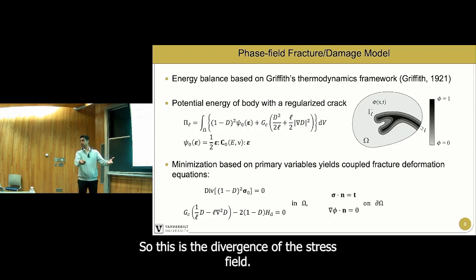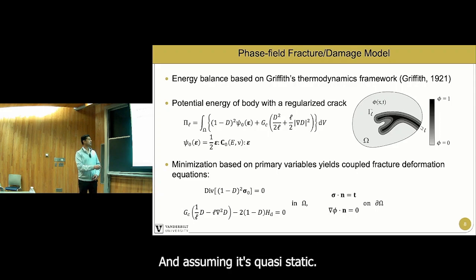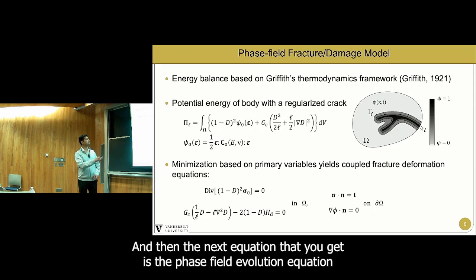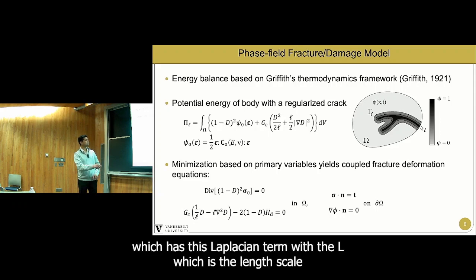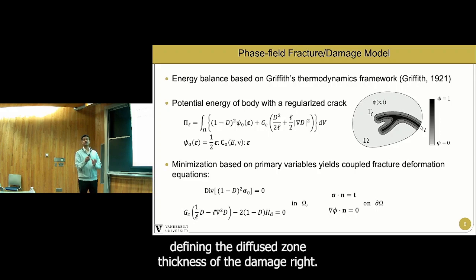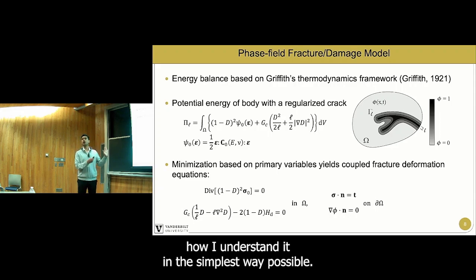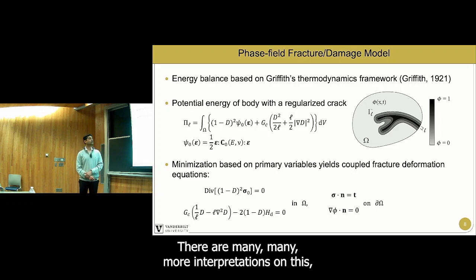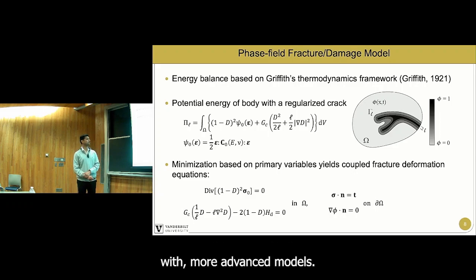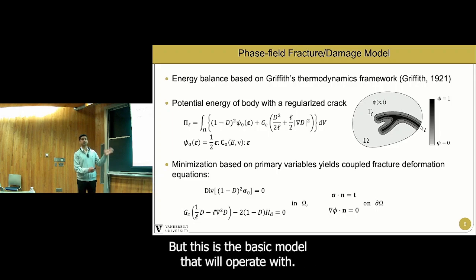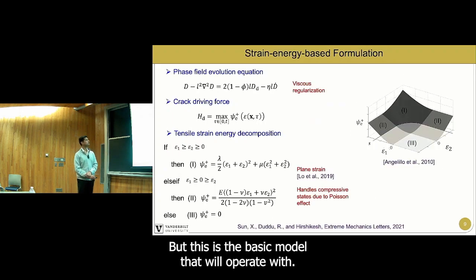So this is the divergence of the stress field, and assuming it's quasi-static. And then the next equation that you get is the phase field evolution equation, which has this Laplacian term with the L, which is the length scale defining the diffused zone thickness of the damage, right? So that's how I understand it in the simplest way possible. There are many more interpretations on this with more advanced models. But this is the basic model that we'll operate with.